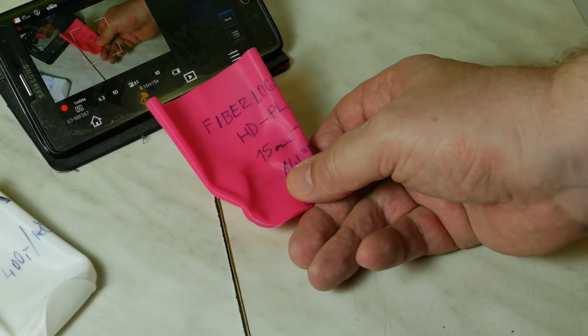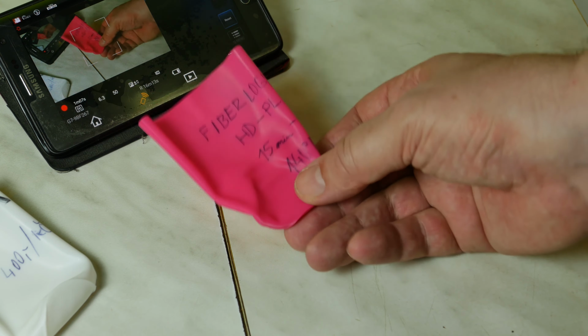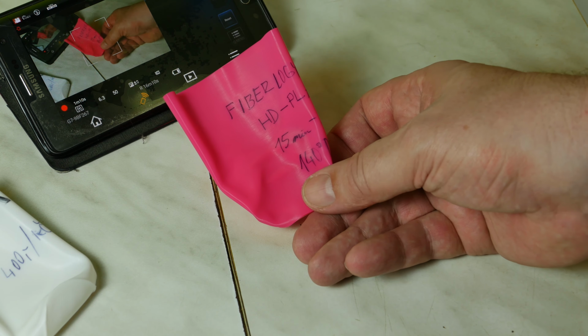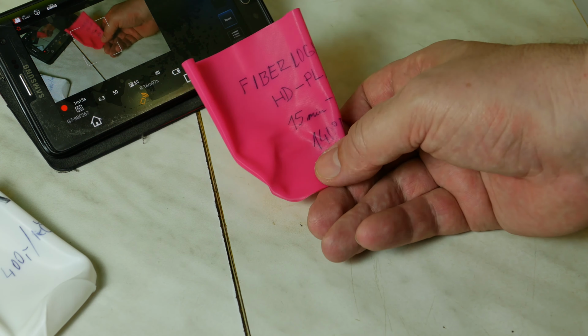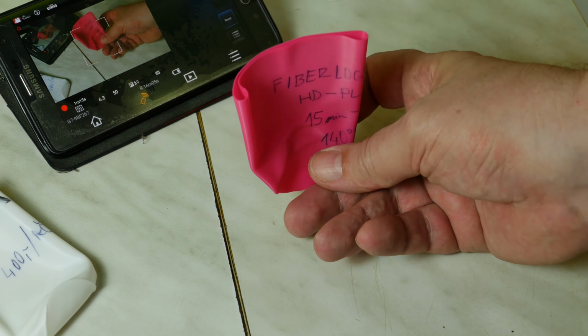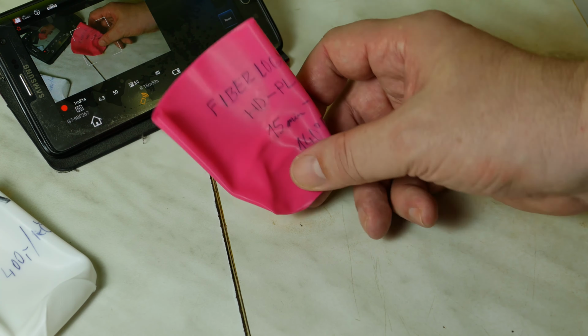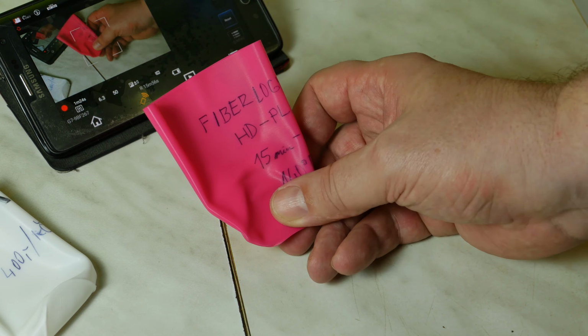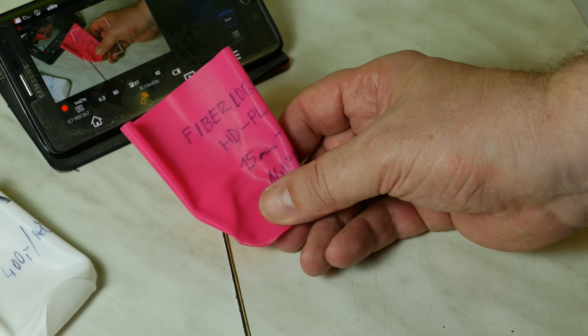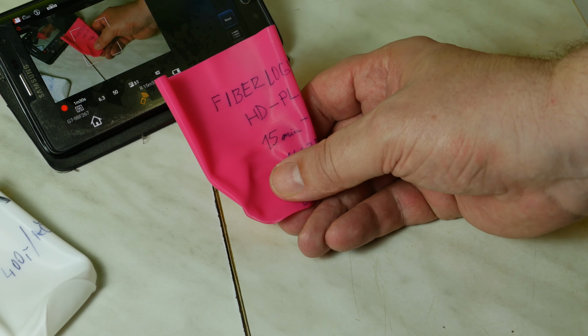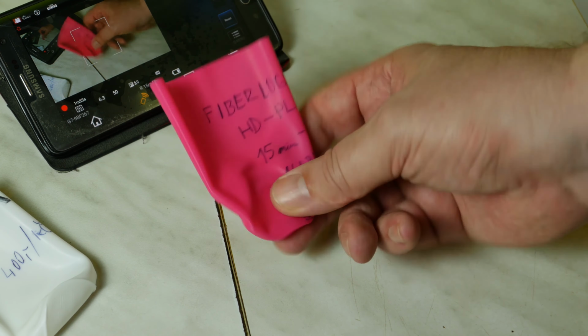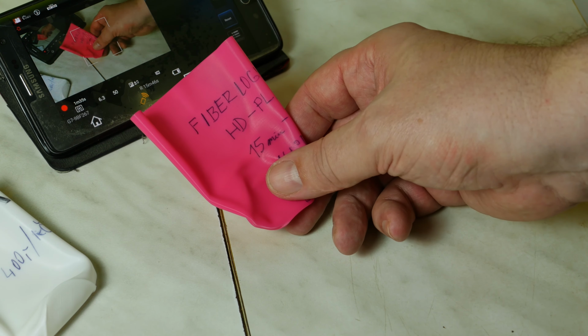About heat resistance or temperature resistance, I mean that if you make the annealing process and you put a higher temperature than 80 degrees of Celsius, your part will be something like that. You really must have the exact temperature of 80 degrees of Celsius during the annealing process, or you will have in your oven something like that. Yes, 80 degrees of Celsius plus minus, I don't know, 3-5 degrees of Celsius.